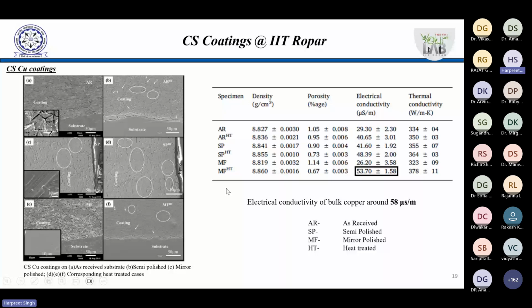So when we deposited, we could get the adherence strength and everything, but still electrical conductivity was a challenge, which was required to be of a certain order. So for that we had to do some kind of heat treatment, as I was telling you. So this is as coated, and this is after heat treatment, right? We could see that after heat treatment, we had better thermal conductivity and electrical conductivity and so on. We also characterized it very nicely, and even 3 mm thickness was achieved, right, which was one of the objectives.